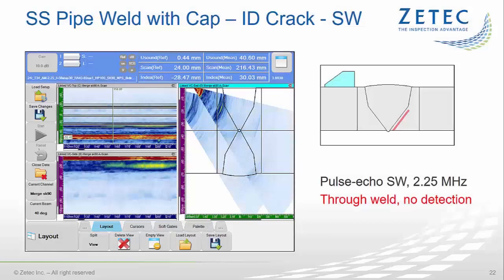This next slide shows merged data obtained with the same 2.25 MHz probe, but with the crack on the far side of the weld. In this configuration, the acoustic beam needs to propagate through the austenitic weld, and the large crack is by no means detected. Increasing the soft gain will only increase the amplitude of the grain noise. The flaw signals are just not there.